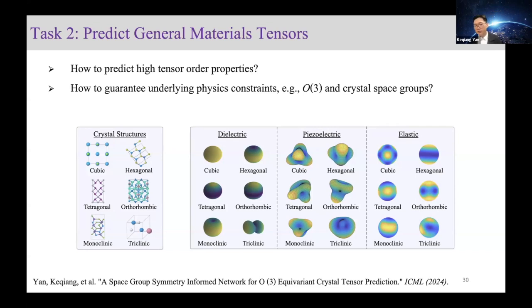So here I show the relationship between the degrees of freedom of tensor properties and the symmetry of crystal structures. For example, the cubic structure has the highest level of symmetry, which means if you reflect the structure by the YZ plane or XZ plane, or if you rotate the structure by 90 degrees, it will map back to itself. But for other systems like triclinic, there is no symmetry at all, and whatever transformation you apply to the structure, it cannot map back to itself. And this kind of symmetry will actually influence the freedom of